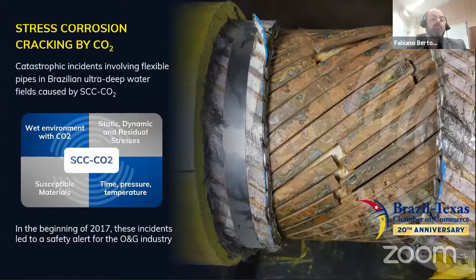What we know today is that the main ingredients that trigger the failure mechanisms are a wet annular environment with water and carbon dioxide, CO2, the stress state of the structural armors, the material susceptibility of metallic layers to corrosion cracking, and the exposure time under the influence of pressure and temperature. Besides that, the uncertainties regarding the speed of damage initiation and failure propagation led to several uncharted operational risks. In other words, it's a silent and invisible failure mechanism that can substantially reduce the pipe service life from hundreds to less than a dozen years.